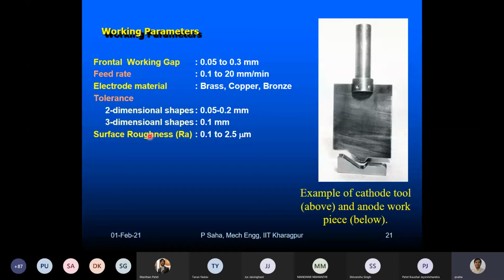Okay, surface roughness, as I said, you cannot really go for a nanometer finish, something between 0.1 to 2.5 micron, mostly in terms of micron. Okay, and tolerance wise, if we suppose we want to have a dimension of 100 millimeter, to what accuracy can we do? For a 3D shape, we can get something around 0.1 millimeter, for a 2D shape 0.05 to 0.2 millimeter.